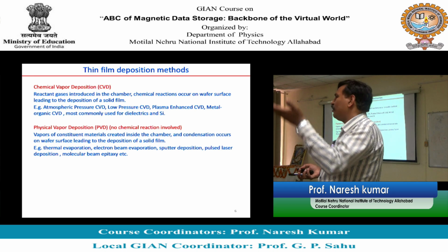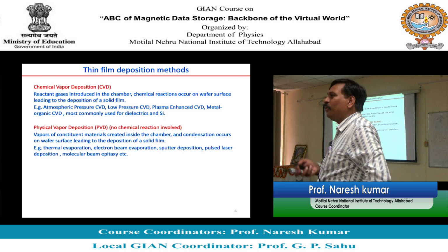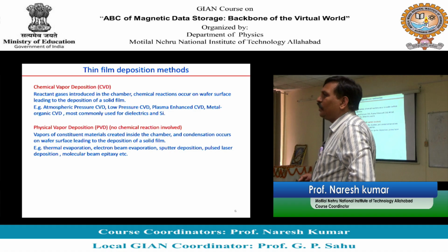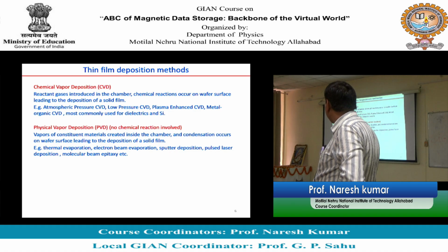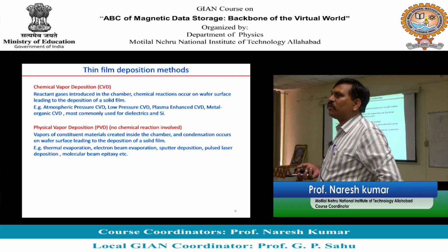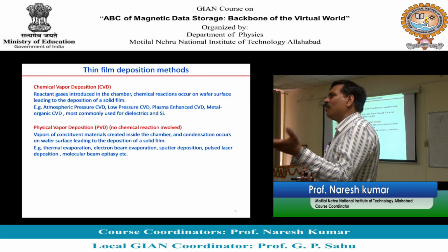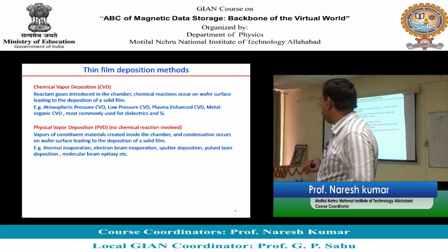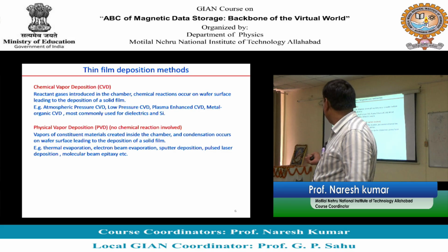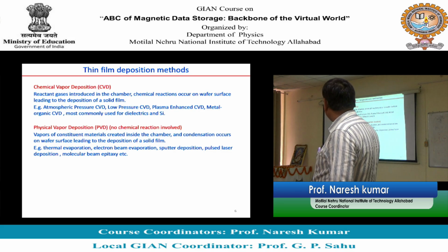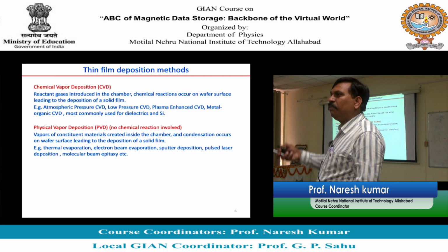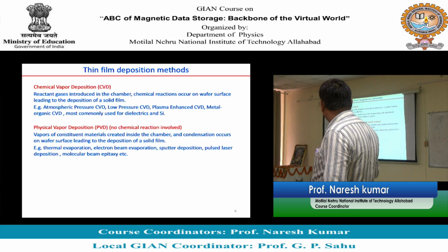So evaporated target material will go and it will form the contacts. So that can be used for making contacts. In fact, this can also be used to deposit oxides. Those who are working with zinc oxide, very commonly people use thermal evaporation. Then similarly, you have electron beam. You take a beam of electrons and you deposit the films.